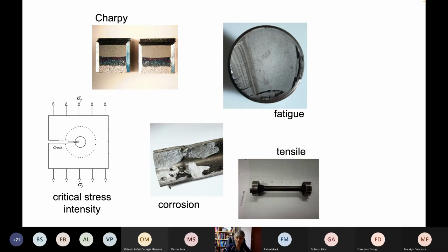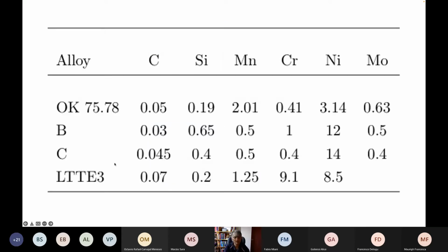Okay, so how do we do this? We have a lot of experience in designing welding alloys. And this is a commercial alloy. Quite straightforward. All of these contain a very low carbon concentration because we don't want to produce martensite. There's a certain amount of silicon and manganese added for deoxidation, because remember, you're pouring the liquid without any of the normal refining processes that we implement for normal steels. And there's a certain amount of hardenability required to avoid high temperature phases. So this is a commercial electrode which transforms at a high temperature of about 450 degrees centigrade.